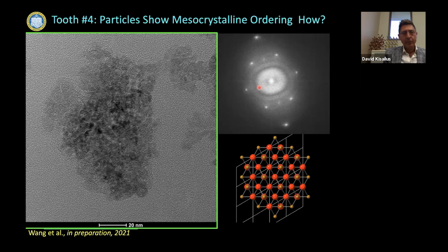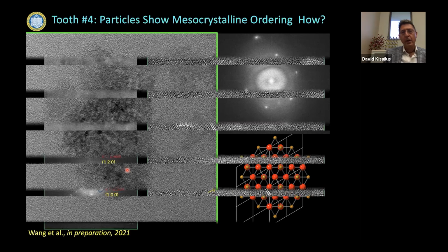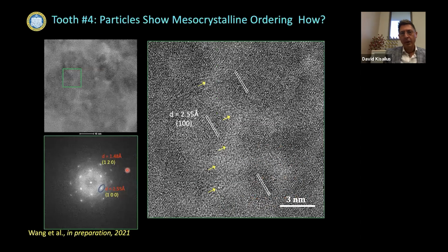And so how does this form? I mean, we have primary domains that are only a few nanometers in diameter that form this highly oriented structure. Is there something guiding this? And this is, again, unpublished data, but work in progress, where we found that the underlying structure to these mineralized particles actually is an organic scaffold. This just shows some amorphous regions separating two highly oriented domains within the particle.